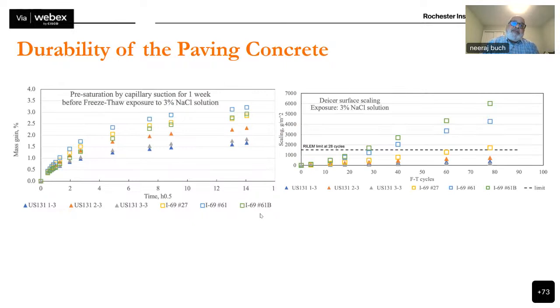We also then ran scaling tests. And again, these tests are critical, especially in places where concrete is exposed to freeze-thaw damage. There are two parts to the scaling test. One is you determine the moisture absorption of the concrete, and then you run the scaling test. The way you run it is you flood the concrete with a solution of sodium chloride for a certain number of hours, then you drain the sodium chloride and freeze the sample. You expose the concrete to a number of cycles of sodium chloride and freezing, because the sodium chloride will prevent the freezing. And when you freeze it, the moisture inside the concrete will freeze, and if the concrete is susceptible to freeze-thaw, you will get fracturing.